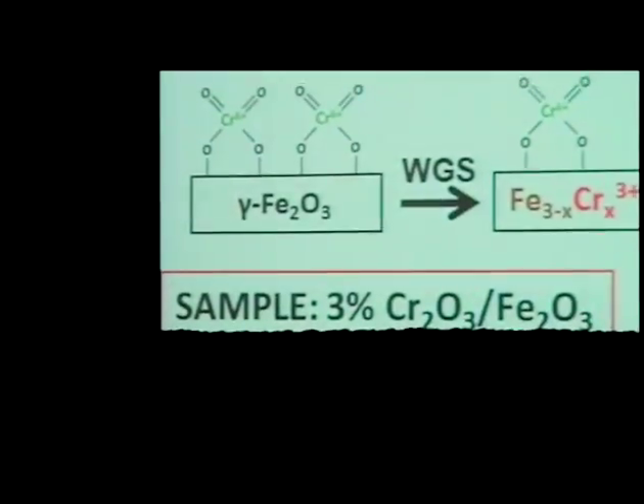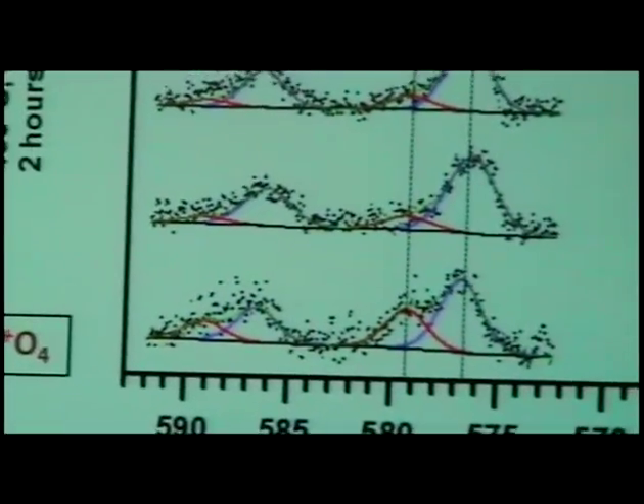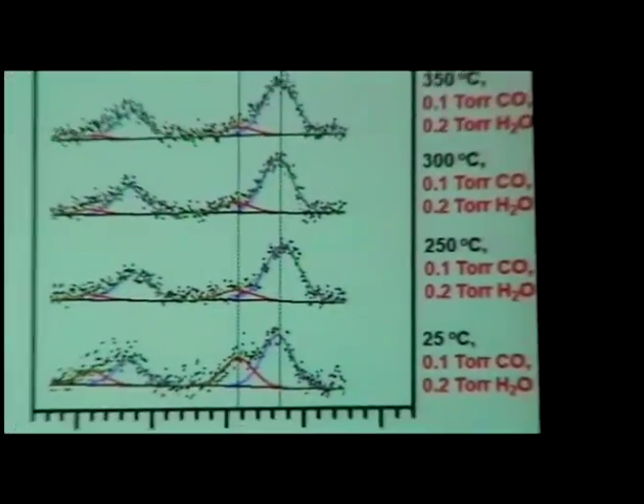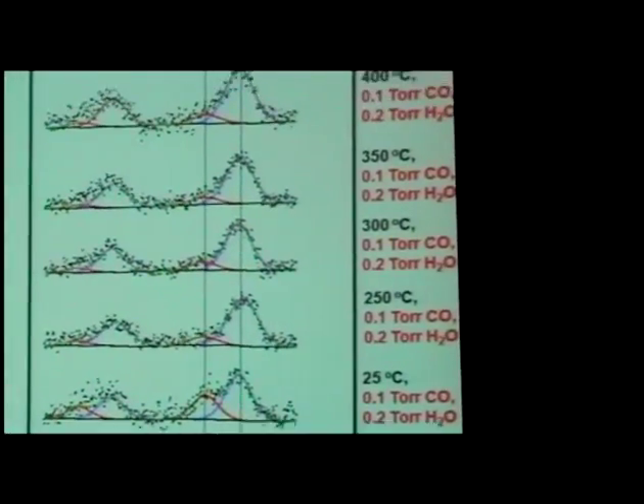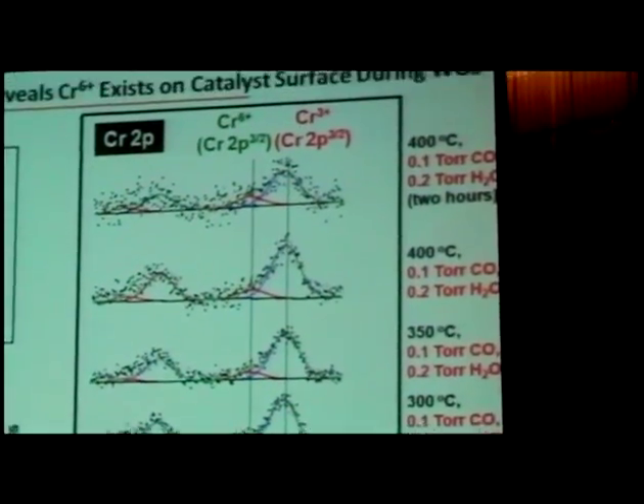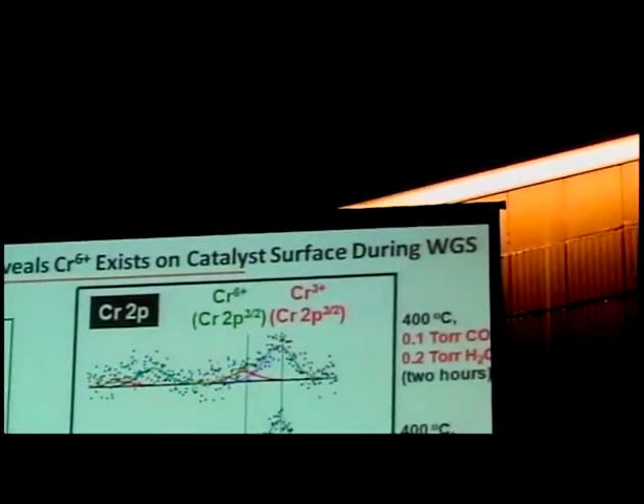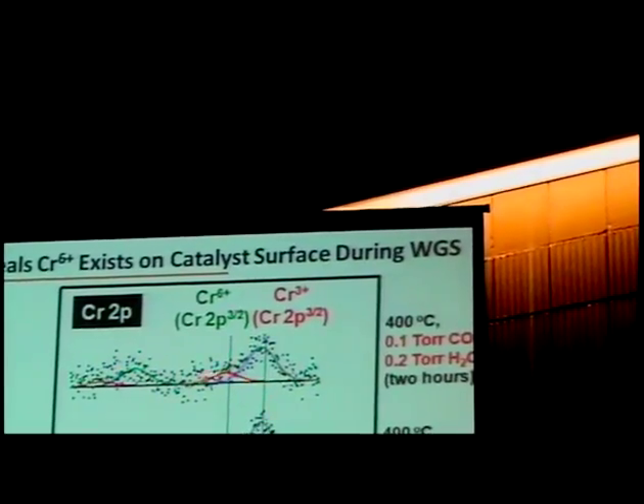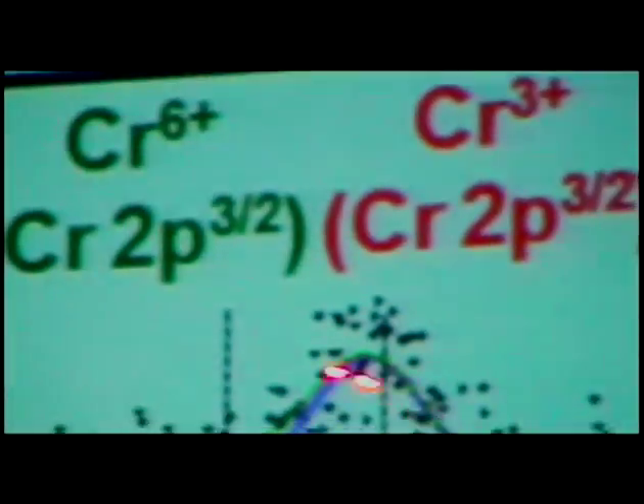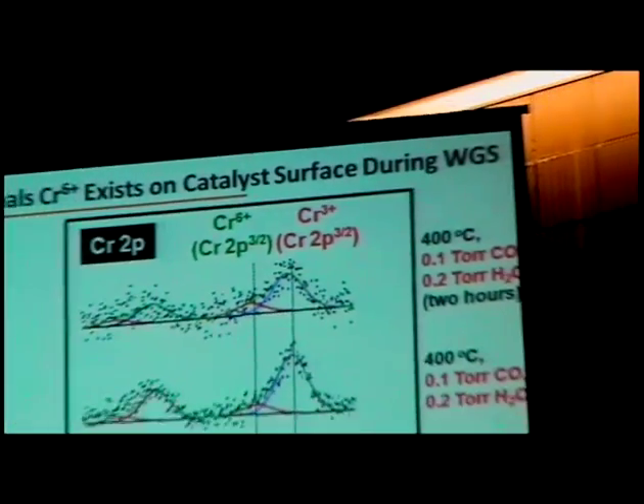And here is the starting point at room temperature, and you have here the peak for chromium 6 and chromium 3, because now we're trying to see what's on the surface. So we know we start off with this, and during the reaction, the question was, is there any chromium 6 left on the surface? And you can see that there's still a small amount of chromium 6 left, even though we're creating a lot of chromium 3, which is subsurface chromium.